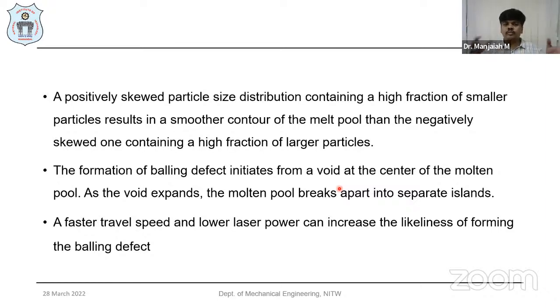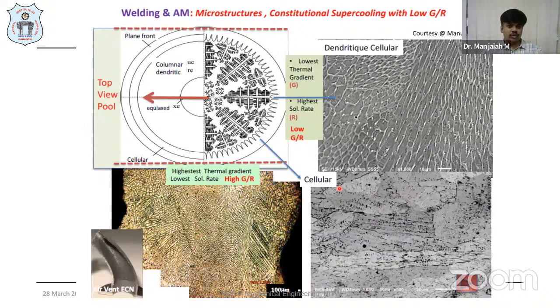As the voids expand, the molten pool breaks and creates non-continuous beads, like separate islands. Even a faster speed and lower laser power can increase the likelihood of forming balling defects. These kinds of defects are going to be created.